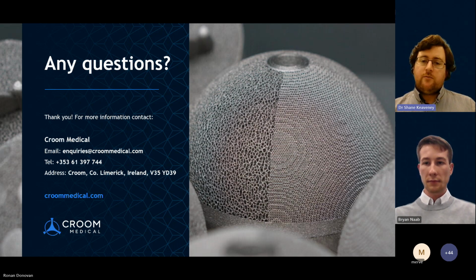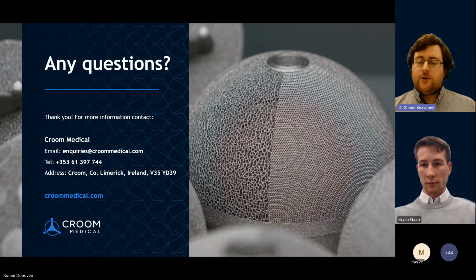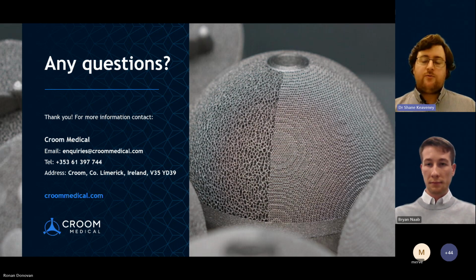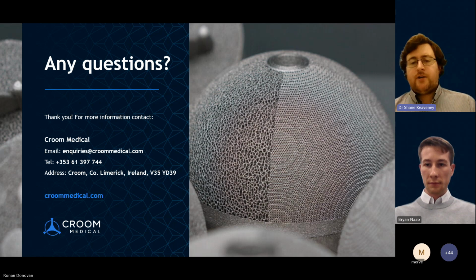So what we normally do is we can print the sample with a solid, lattice, then solid, and have that loaded into our tensile tester to pull the structure apart. Or we could print solid, lattice and then bond that top lattice, that exposed lattice structure, to a fixture with, say, an epoxy resin. Typically, it used to be FM1000, I think, but there are specific glues we can use for that. But we're really trying to look at a glue that's stronger than what we need the porous structure to be. It's a very important test for the bonding of lattice to solid.